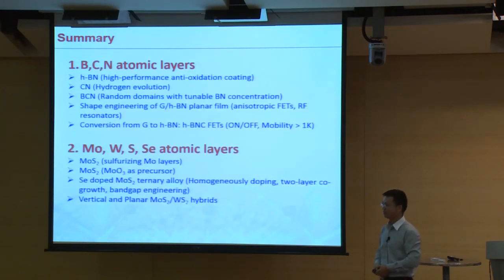Okay. A very brief summary of our work. The first work is the BCN atomic system. We prepare the boron nitride. We can prepare atomic carbon nitride. Also, different approaches to the BCN system with random domains, with shape engineered domains. And we can convert graphene to boron nitride with high quality. And the BCN has very interesting electrical transport with a very high on/off ratio and mobility.